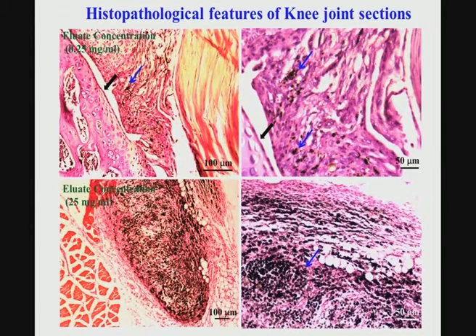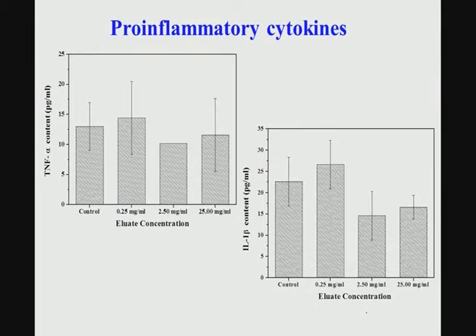Now, when it comes to the knee joint sections, where these hydroxyapatite barium titanate particulates are injected, I have put some arrows here, and what these arrows indicate is the accumulation of the hydroxyapatite barium titanate particulates, distributed over a large region, particularly along a particular region. But it does not show very altered cell morphological features in these tissue sections, but certainly it shows that these particulates are not uniformly biodistributed in different organs. Instead, they are accumulated in the knee joint sections.